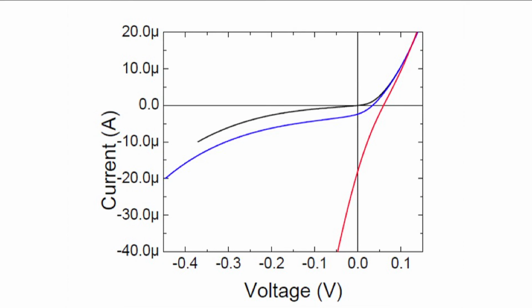And then the red line is when we just shine a black body radiation at 600 degrees Celsius. So not hot enough that you can see it glow red, but quite hot and not very far from the sample. So just blast the thing with light.